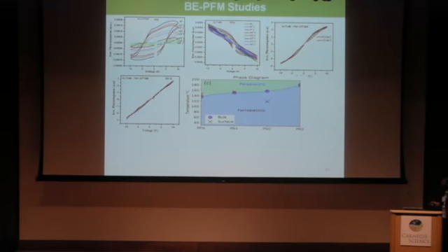So we have carried out some temperature dependent piezo response measurements in order to corroborate the bulk ferroelectric phase transition, and this is the tip induced ferroelectric phase transition. As the temperature increases, the piezo response decreases, and above 125 degrees Celsius the piezo response vanishes. Hence, in both cases, out of field and in field, and this is the room temperature in field minus out of field. It is nonlinear, and in the in field minus out of field measurement above the phase transition temperature, it is highly linear, meaning there is no periodicity.